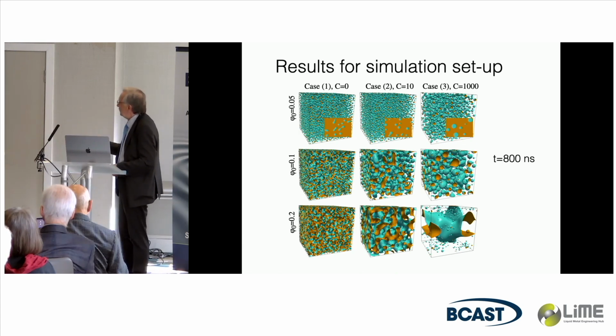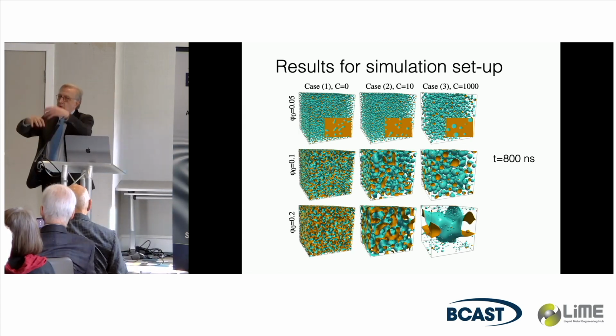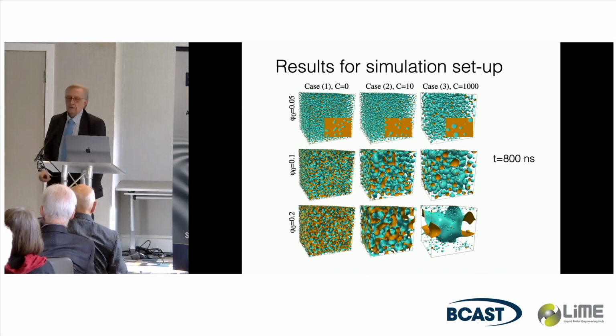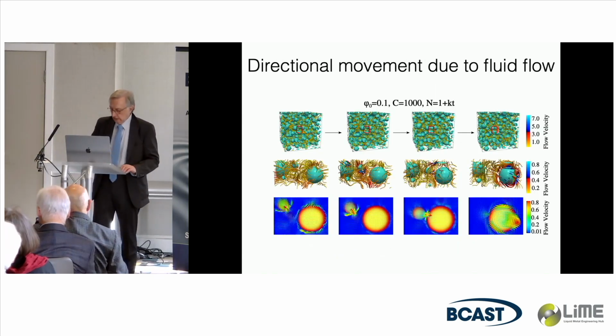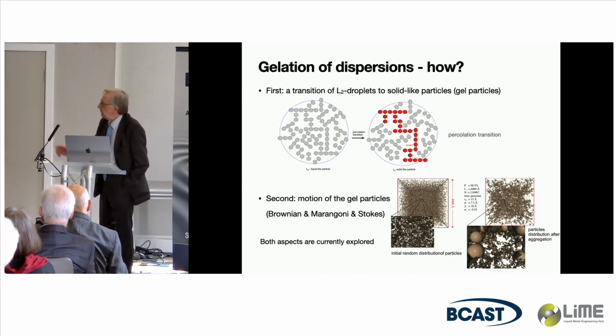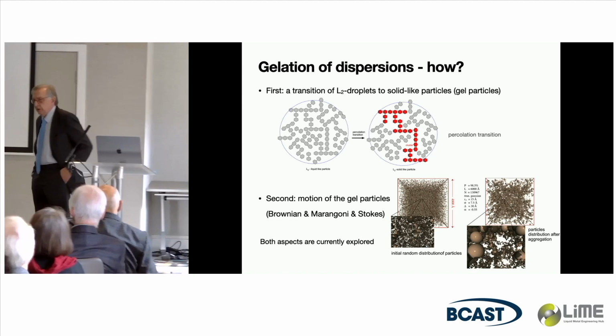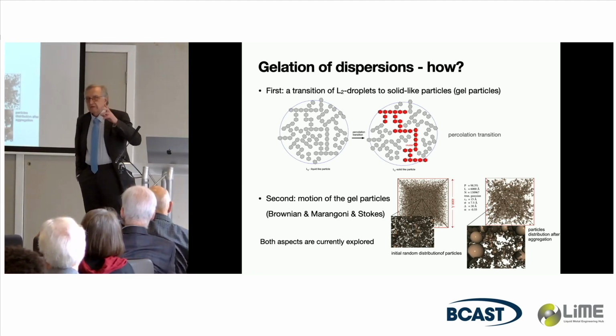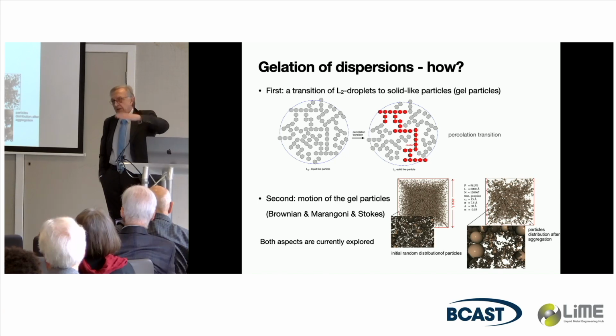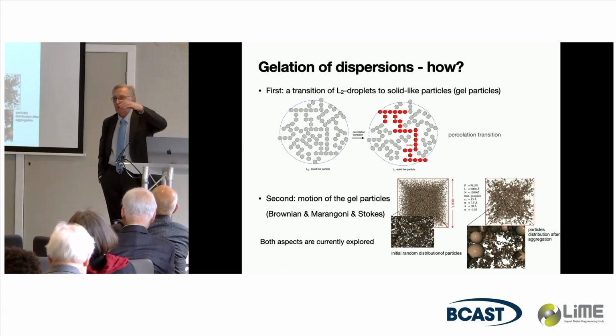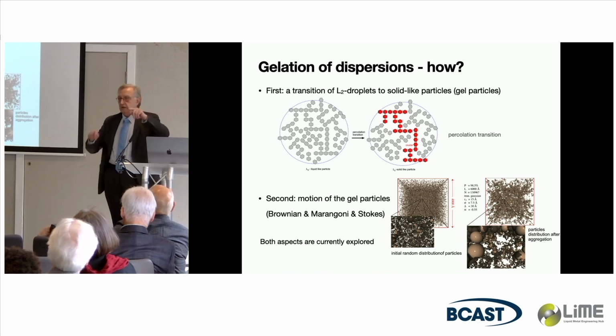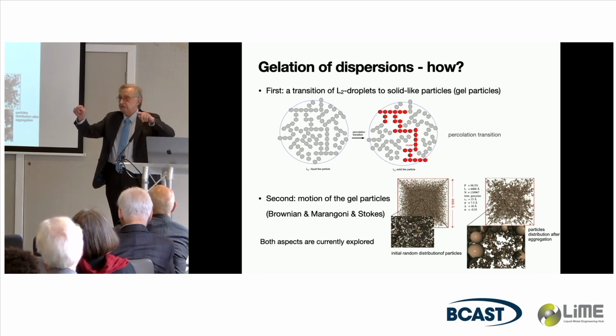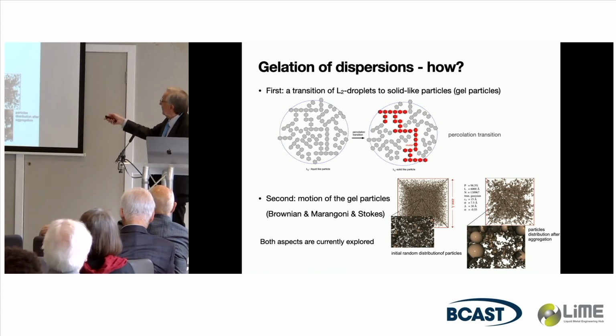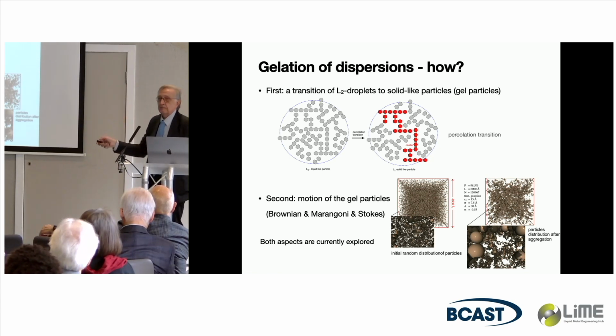If you increase the volume fraction, of course, then the droplets interact much more, and finally they would make a big blob. Well, that's not interesting, and I skip that. And the point is how to now describe gelation. The essential point is, once the liquid miscibility gap evolves and crosses a state point, then a second phase, a polymer-rich liquid phase, appears as a droplet. But the polymer concentration is so large that these polymers do a very simple thing. They do a percolation transition.